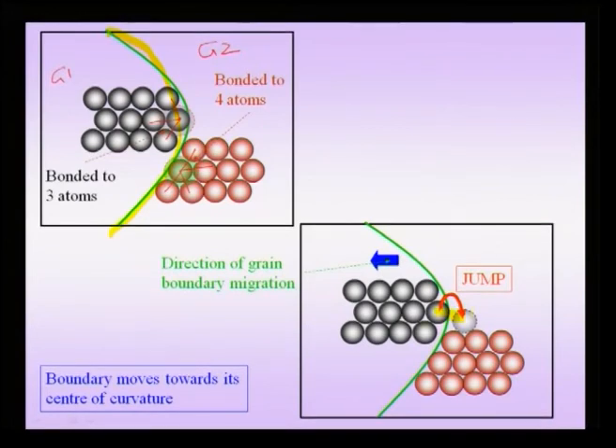Of course, it has to jump over a small barrier, but this jump can take this atom from grain 1 to grain 2, and then it becomes part of grain 2. In the process, its coordination number has increased from 3 to 4. That means locally the energy of the system is going down when the atomic jump takes place.